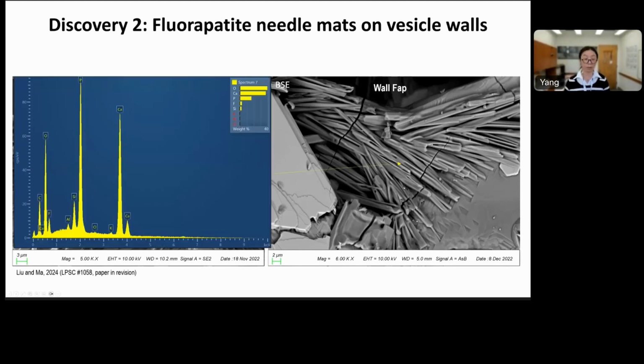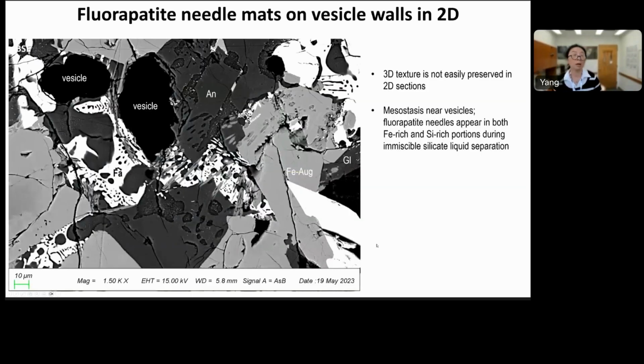And to show their chemistry, this is not a clean analysis again, because it's a very small grain. But as you can see, it's calcium, phosphorus, fluorine. Chlorine is really low. So it's mostly a fluoroapatite. In order to constrain the chemistry, again, we look at the 2D sections to help us understand how the minerals on the vesicle wall are related to the rock itself.